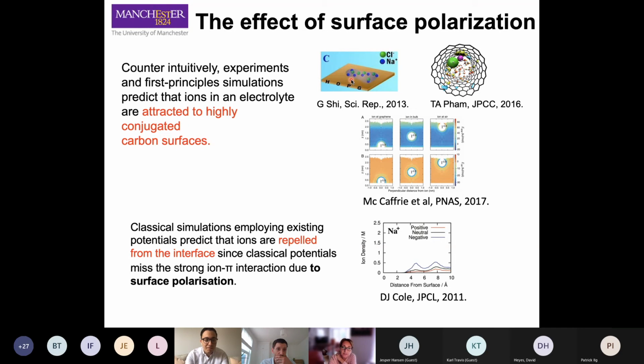Despite the surface being, as I was saying, not reactive at all, some interesting things happen at the interface between graphene and graphite and electrolyte. Basically, anything can stick to the surface due to this electron cloud formed by these pi electrons on the top of the surface of graphene and graphite. And this has been seen experimentally as well as from ab initio molecular dynamics. So we are interested in the interface between graphene and electrolytes. This is because graphene oxide and also graphene can be used for desalination purposes, for example, but this interface is also very much present in a lot of electronic devices.